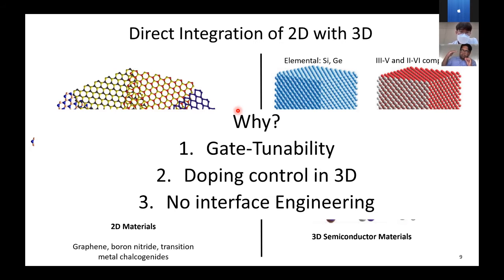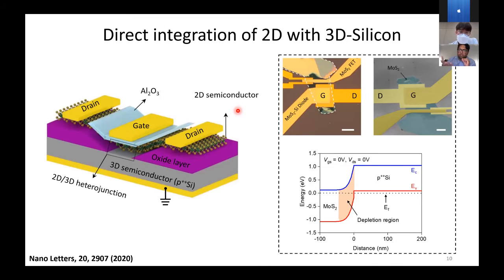And finally, there is interface engineering. If a 2D material can be used to passivate a 3D material surface, then that would achieve the best of both worlds together, and you would not need to re-engineer the 3D interface. This is where we have been experimenting for some time now, using 2D molybdenum disulfide, tungsten diselenide, also materials like black phosphorus and indium selenide, and integrating them directly with silicon in the hope of making a heavily doped PN junction and gating that heavily doped PN junction to make a tunneling field effect transistor, right?